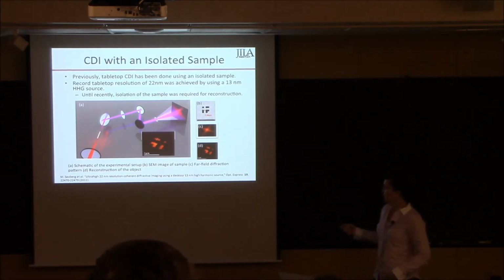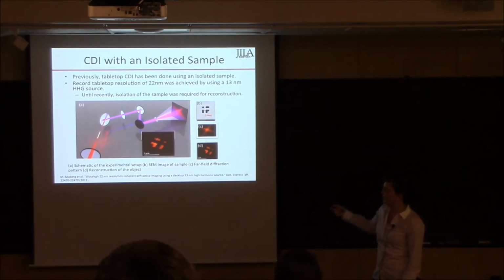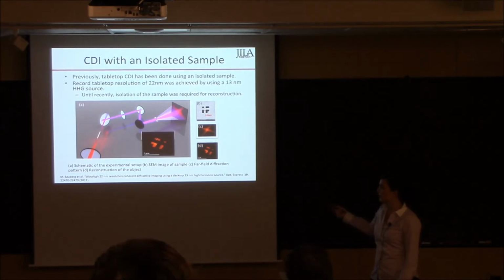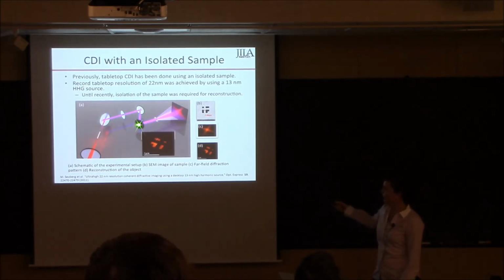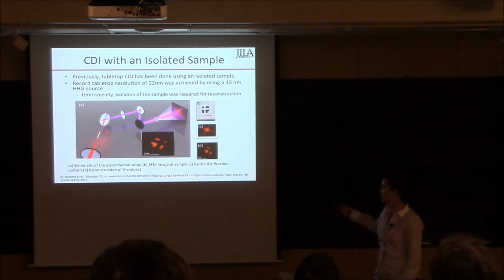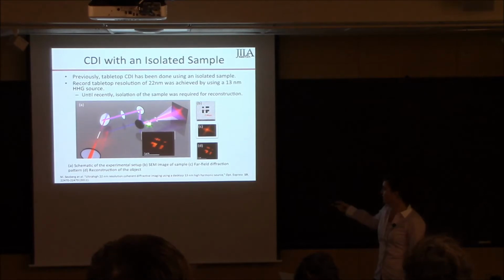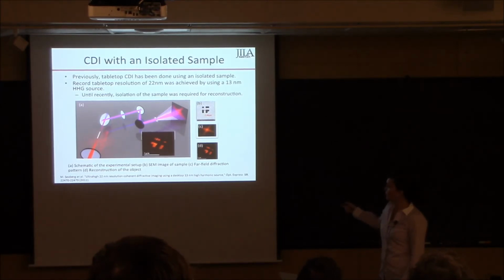So this shows a typical setup for CDI. The IR beam is being focused into the waveguide, and then out of the waveguide comes the high harmonic light as well as the IR. And it bounces off a couple multi-layer mirrors, which selects out the wavelength that we want of the high harmonic beam. And then that hits the sample and it diffracts onto the CCD. So here is a SEM image of the sample and the diffraction pattern that was collected, and finally the reconstruction.